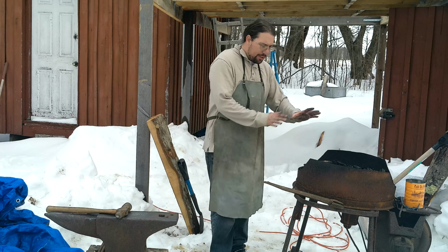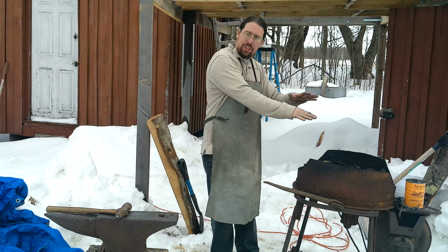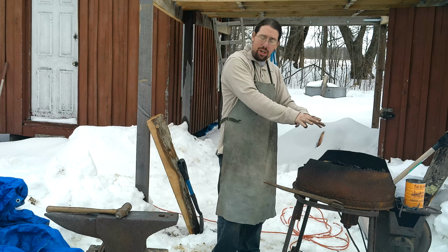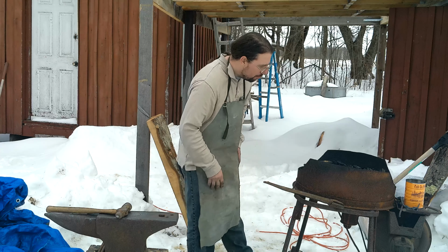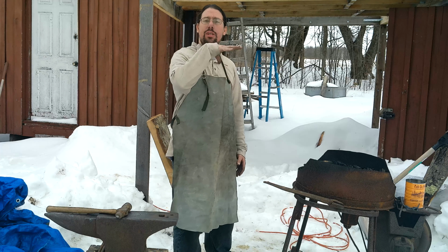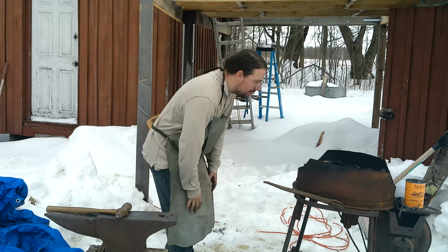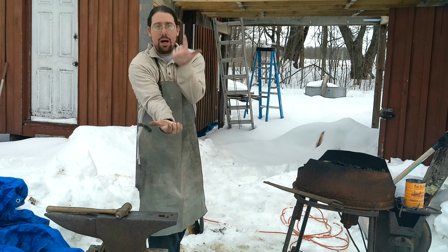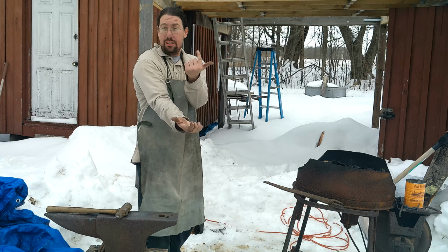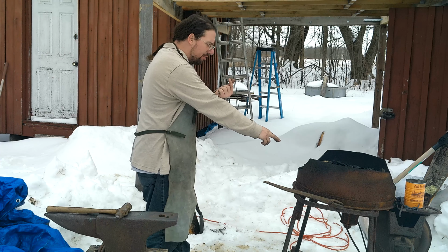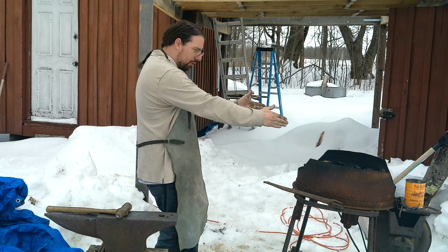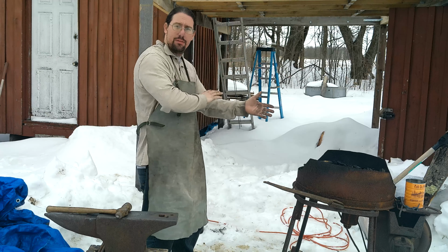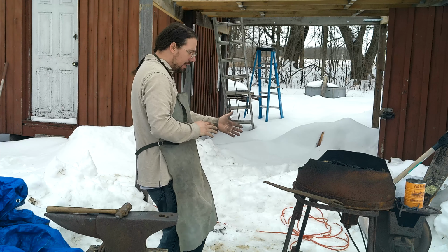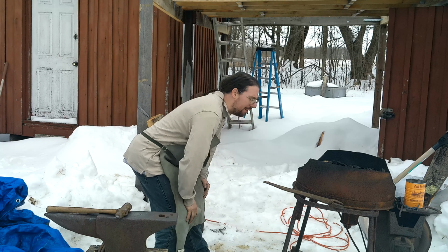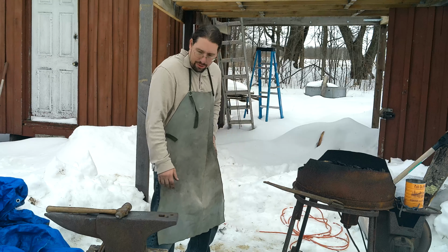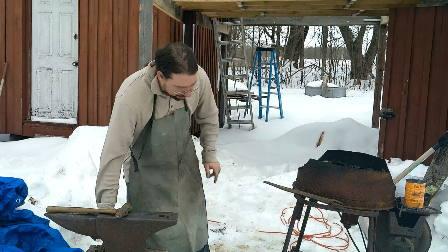And you can control where the heat is by where you position the little clumps of coke that are on top there. More coke on top of your material, it will heat up faster in that region than where it's uncovered. And I have the tip up, so the tip heats up the slowest. So the back is heating up first, and then I'm just watching that temperature crawl out to the tip. Okay? And we're about there.